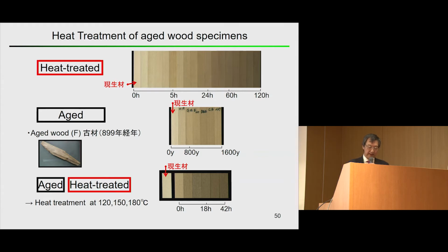This can be proved as well by the heat treatment of wood sample F aged for around 900 years. Those are the heat-treated samples with different treating times, and those are the aged ones. We took some samples, number F, which has already lasted for around 900 years, then heat-treated this sample. Then the color changes started from the initial one, aged 800 years, and went darker and darker as well. So those results show that the color changes of heat-treated wood and aged wood obey the Arrhenius law, so that we can control the color of wood by the heating time and heating temperature.